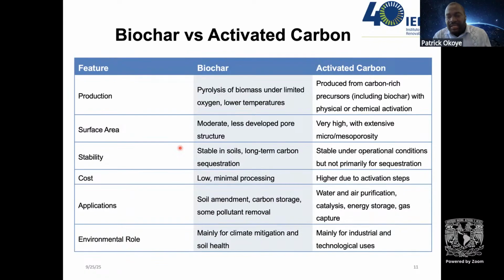So in the production, of course, we use mainly pyrolysis for biochar under limited oxygen and at a lower temperature. But for activated carbon, because we need a carbon-rich material, we usually use higher temperature, and in fact, the production could go towards physical or chemical activation. And in a bit, I'm going to talk about the difference between physical and chemical activation.